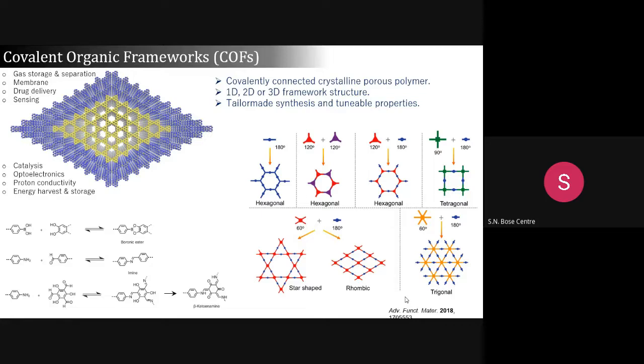So generally, this kind of synthesis takes 3 to 7 days, where during the reaction inside the matrix, some bonds will be broken. Here you can see the bonds will be broken, which can eventually during the reaction rectify itself and form the crystalline lattice. So that is why we generally use the dynamic bonds, which reversibly can undergo making and breaking of this system. Later, this kind of beta keto also has been introduced. So initially formation of the reversible system, then followed by locking of this system by beta keto. And this chemistry has been introduced by Professor Rahul Banerjee, who is working in Kolkata.